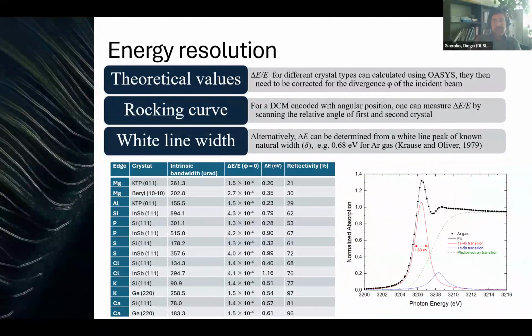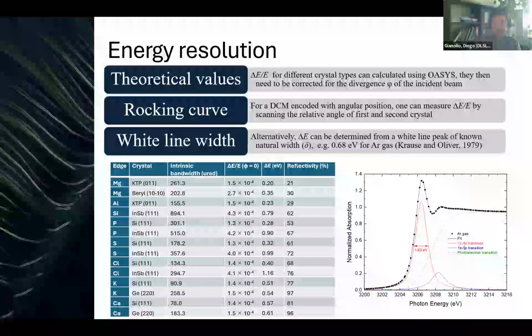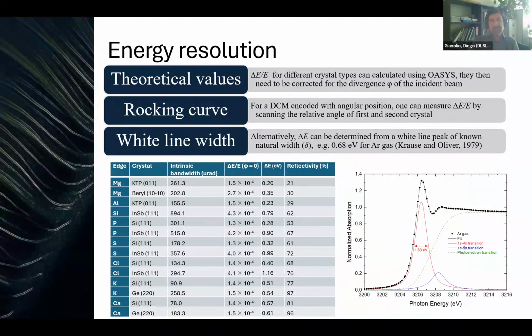Another problem that we think is maybe even more important in the tender X-ray range than in the hard X-ray is the energy resolution. As you probably know, the core hole broadening that we have at hard X-ray is much smaller than at the tender X-ray edges. So when you want to compare spectra collected at different beamlines, it's important to be aware of what the energy resolution is. There are different ways to measure the energy resolution.